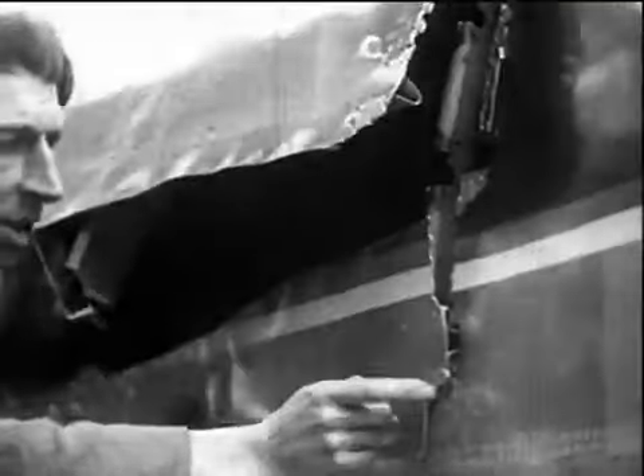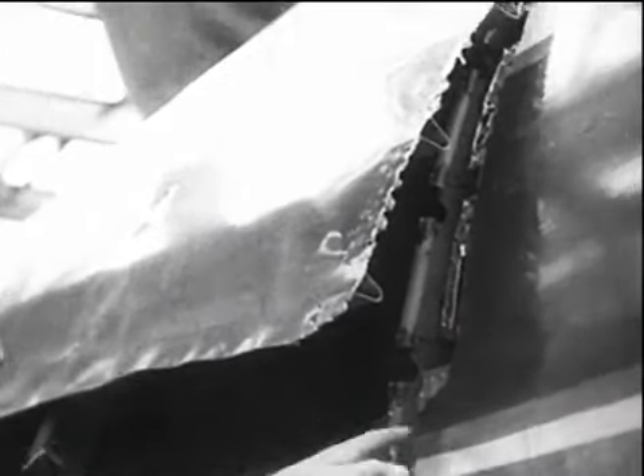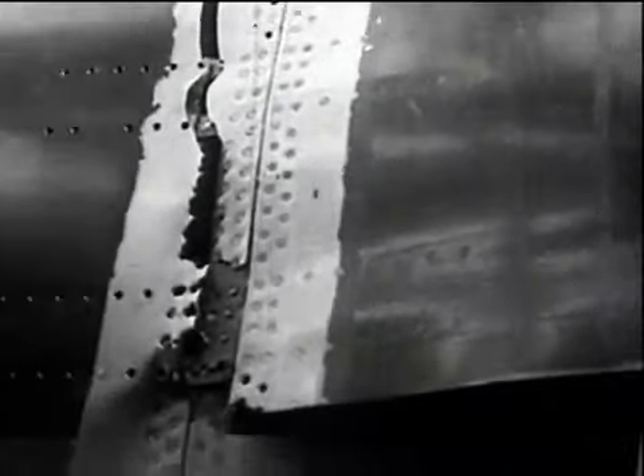A small fatigue crack in the skin of a rivet near an escape hatch is considered to be the start of the failure, which developed rapidly. The damage was then repaired, and also a crack believed to be the beginning of another major failure.